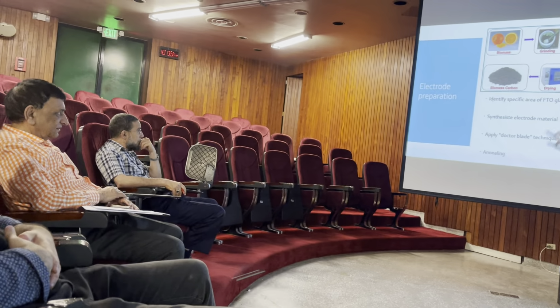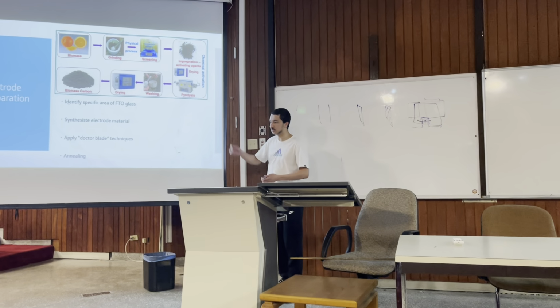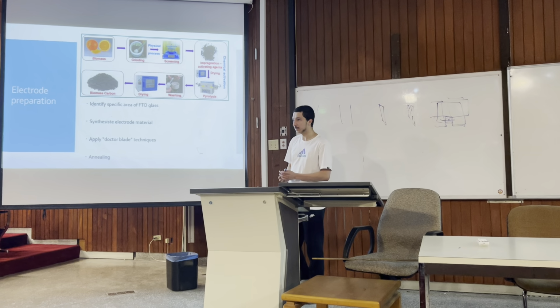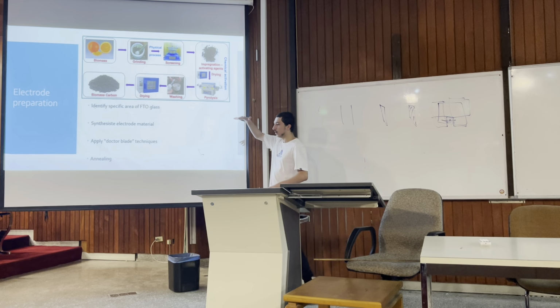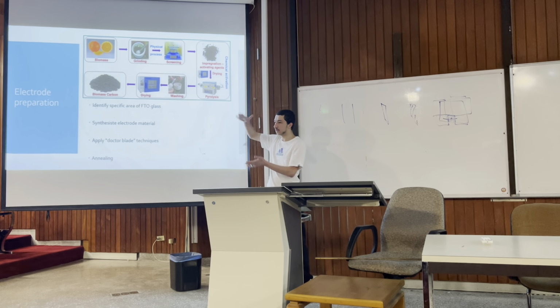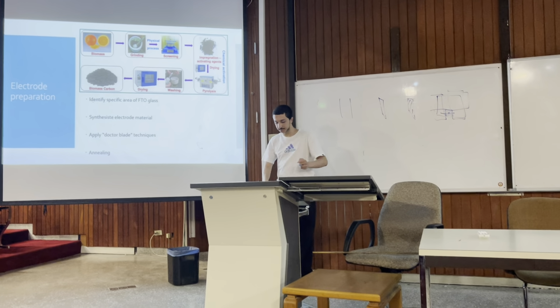After we do all of this, we do annealing. Usually we reach temperatures of 400, 450 degrees Celsius to make sure that the material that we deposited, carbon in this case, sticks to the FTO glass.